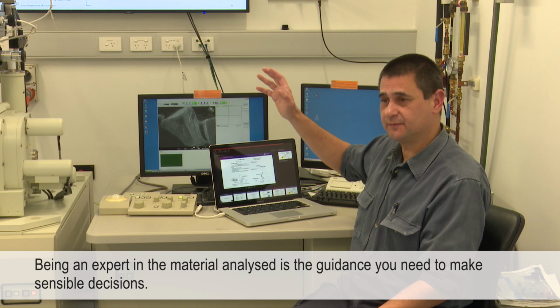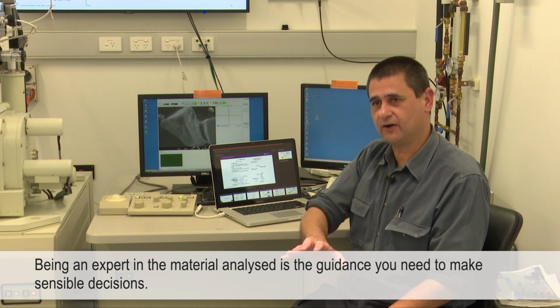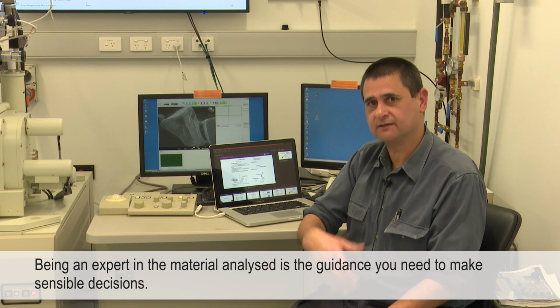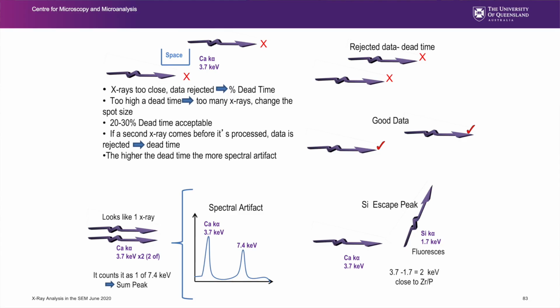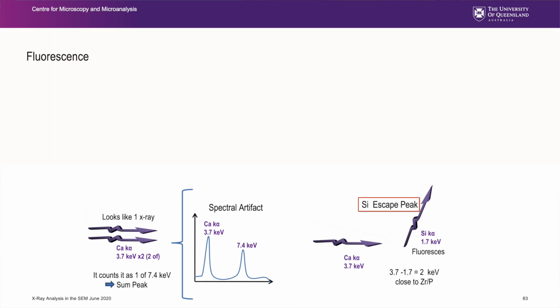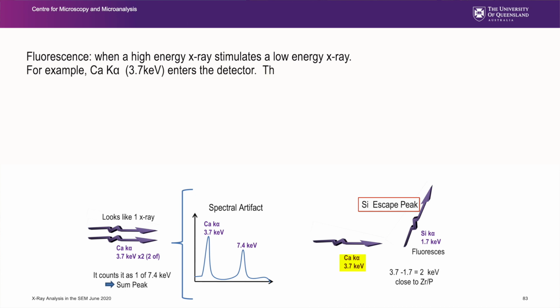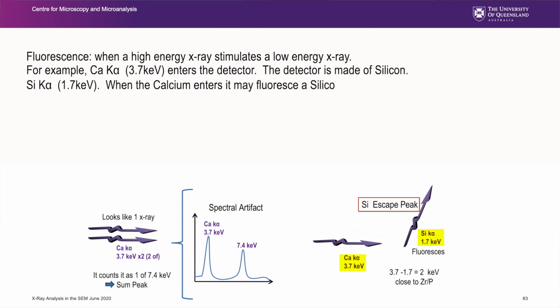Sometimes being an expert in the material is the only guide you need to make sensible material decisions. And now the other artifact is a silicon escape peak. We've already talked about fluorescence. That's when a high energy X-ray stimulates a low energy X-ray. Again, for example, calcium K-alpha, 3.7 keV is entering my detector. My detector is made of silicon. Silicon K-alpha, 1.7 keV. When my calcium enters, it may fluoresce a silicon X-ray.